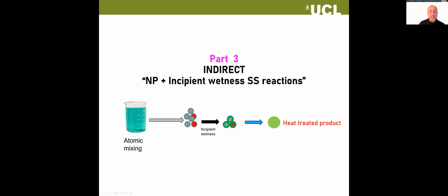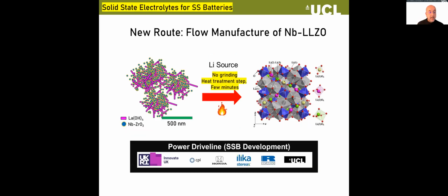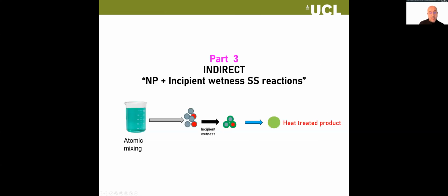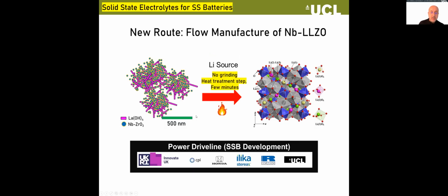The idea here is that you've got an intimate mixture between the green and the other oxides. And when you heat treat them, again, diffusion distances will be small, and you'll get a really nice, efficient reaction without grinding. So here's the material. This is niobium-doped lithium lanthanum zirconate. So what we've got here is the lithium is added at this stage by incipient wetness, but the elements niobium, lanthanum, and zirconium, the 3 elements, are added initially from our solution and form a precipitate of our oxide or hydroxide. It doesn't really matter. So we take that mixture, and this one actually contains what looks like lanthanum hydroxide rods, and then some kind of solid solution of zirconium and niobium. It seems to be the preferred precipitation of this nanoprecipitate. And what you can see here, these rods are favored by this hydroxide structure.